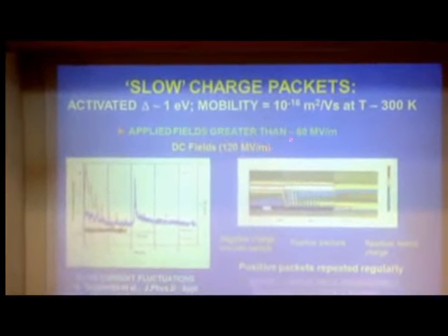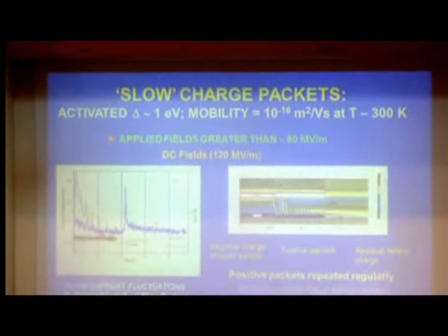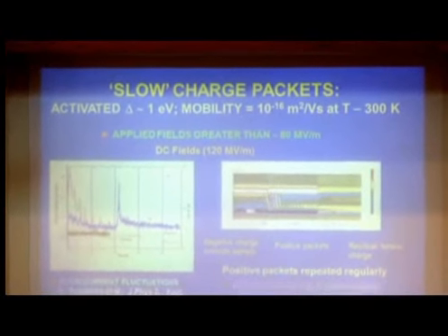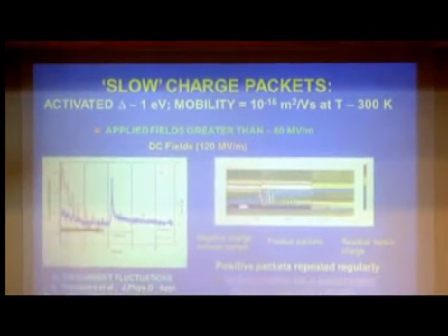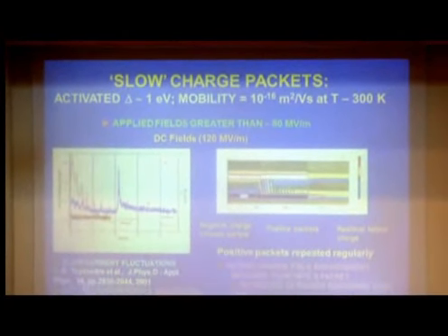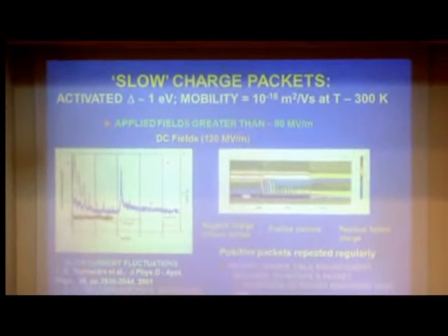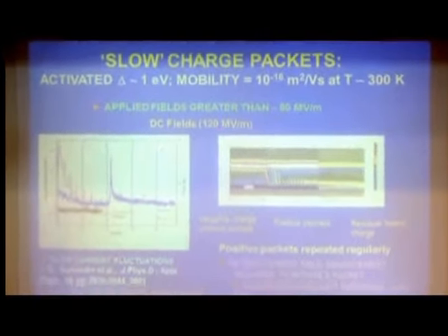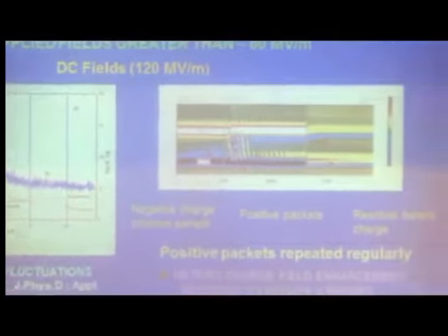And they occur at applied fields in excess of 80 megavolts per meter. These are usually materials that have some chemical impurities. If you have rather good materials, it's a higher value. Both these experiments are complementary, carried out at the same kinds of fields, on the same materials. Well, not the same individual samples, but the same materials.